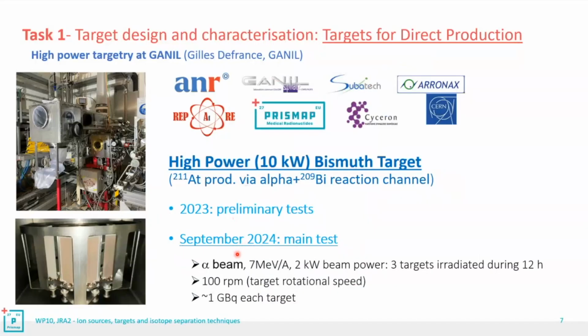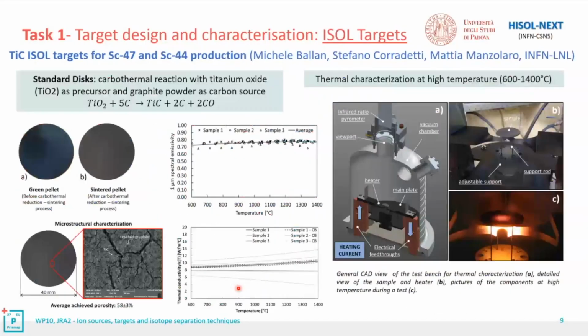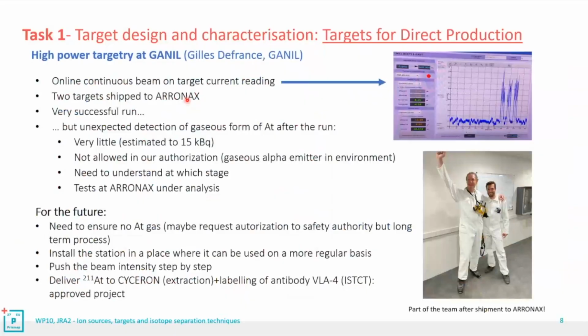They irradiated 3 targets with alpha beams at high energy, 7 MeV per nucleon, and they produced 1 gigabecquerel for each target. 2 of them were dispatched to ARRONAX for the post-processing phase. I would say that this test was successful, but with an unexpected detection of gaseous astatine after the run. So now the ARRONAX group, the Daniel group, is working to fix this problem, and they are ready to deliver astatine 211 to Cyceron for extraction and labeling in the context of this approved and financed project.